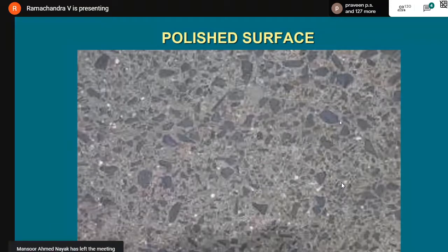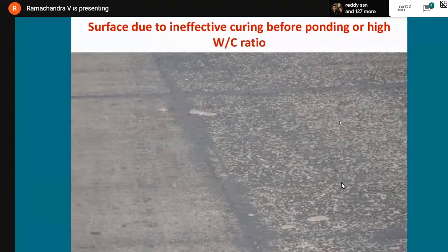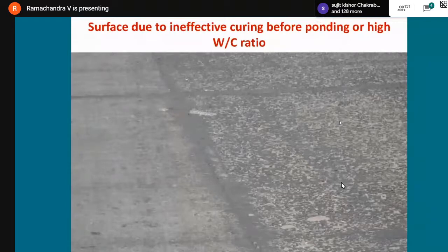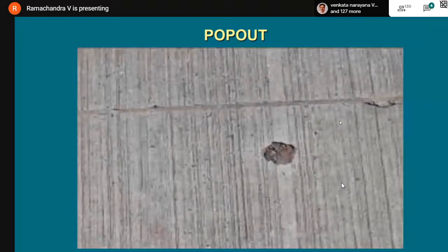Now, if finer aggregates go off, you will get what is called a polished surface. This polished surface exposes the aggregates. These exposed or polished aggregates, you will see the effect like this. This happens due to ineffective curing before we do ponding, or a very high water cement ratio. You can see one part of the road is good, the other part of the road is a problem. Therefore, the concrete was probably the same, but then a high water cement ratio was there. That was a different batch of concrete with different properties. Therefore, you face this problem.